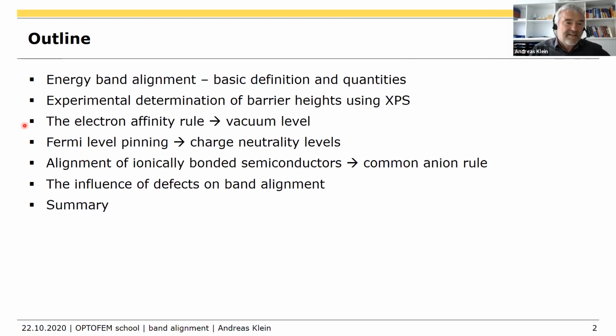So historically, the barrier formation between metals and semiconductors was first addressed by looking at the alignment of the energy levels, in particular the alignment of the vacuum energy, which was done by Mott and by Schottky, and that's why this is called the Mott-Schottky rule. Later, actually not really much later, people realized that the Schottky barriers, the barrier heights at these metal semiconductor junctions, do not really follow what is expected from this vacuum level alignment. This observation was then called Fermi level pinning.